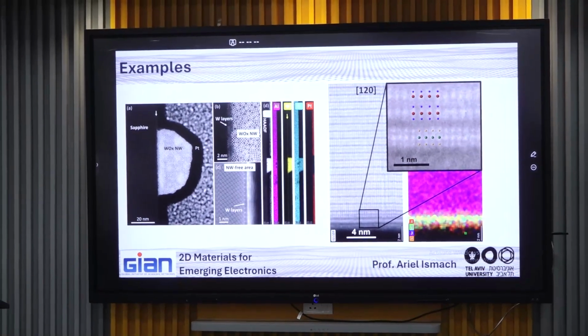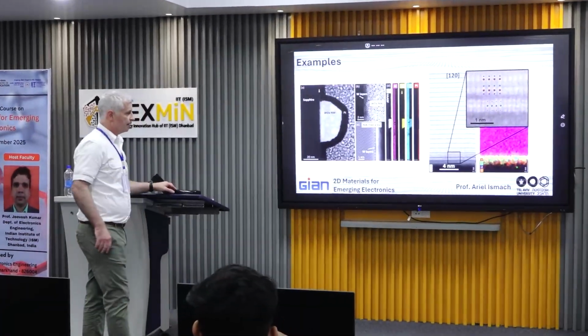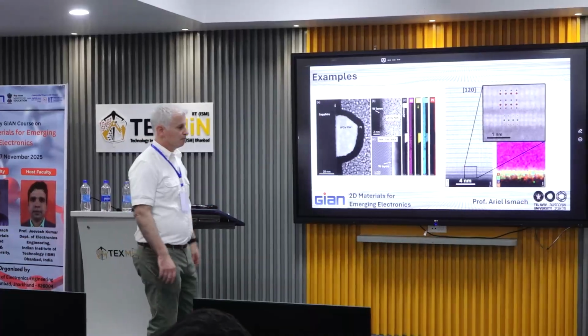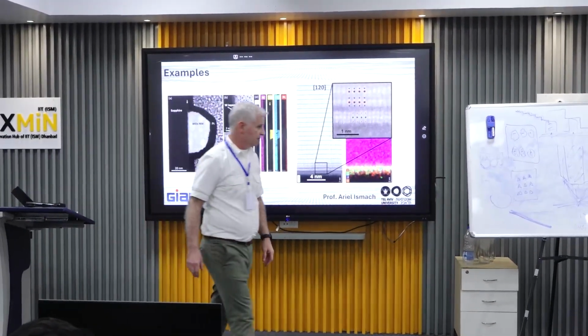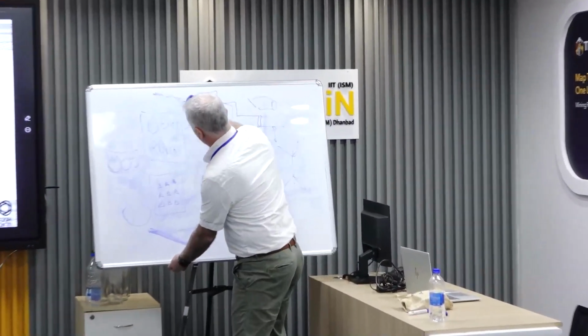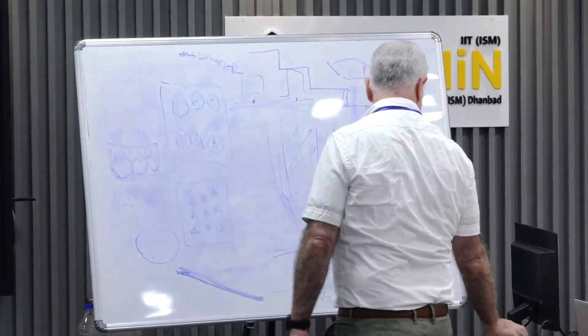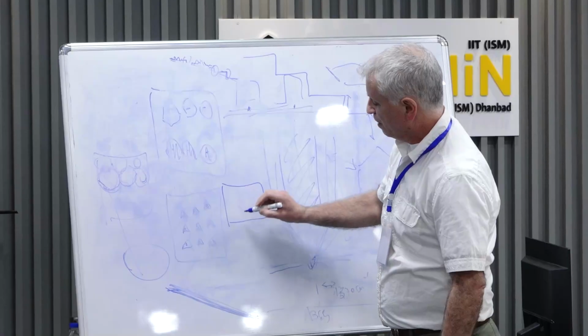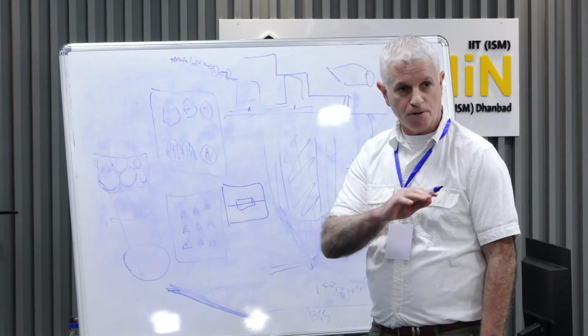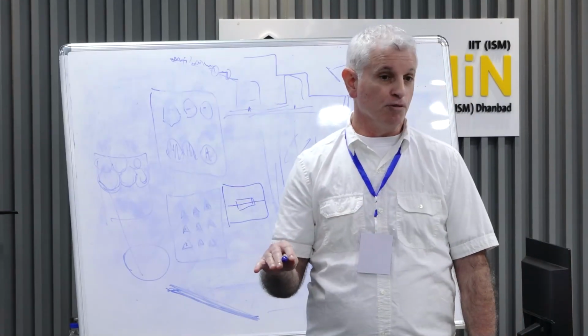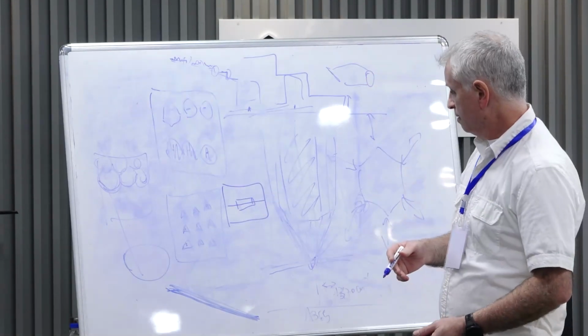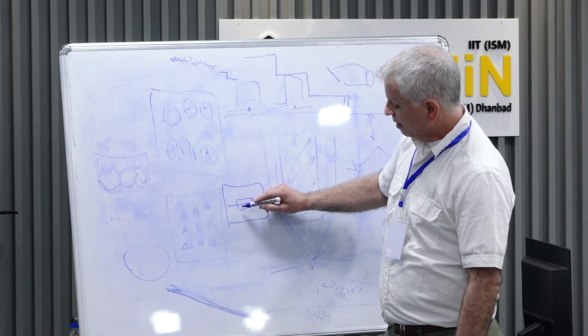Okay, cross section. For this specific sample, the best way to do cross section is by focused ion beam. Focused ion beam is also a complex process, but of course many people do that today. So what you do, you start from the material, let's say top view of a plate, whatever you want to do cross section. First of all, you need to deposit on top of it a protective layer, and you need to choose the protective layer according to the materials that you have in the layer, so they don't confuse the chemical analysis. Protective layer, and then you need basically to start digging with the focused ion beam.